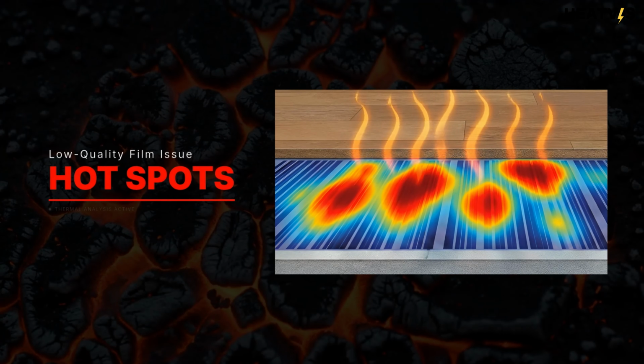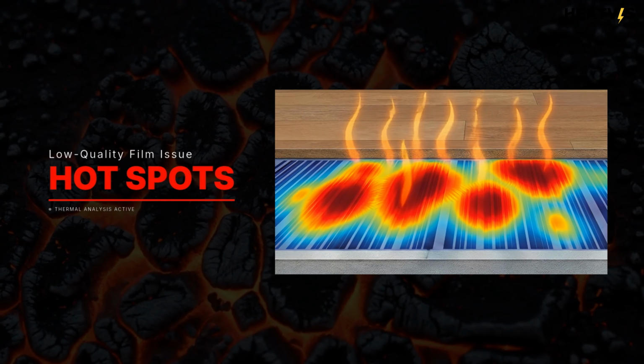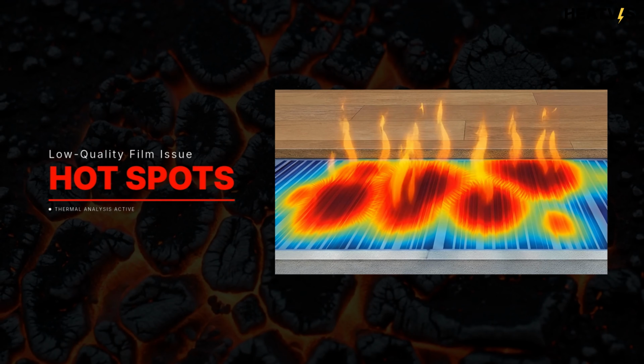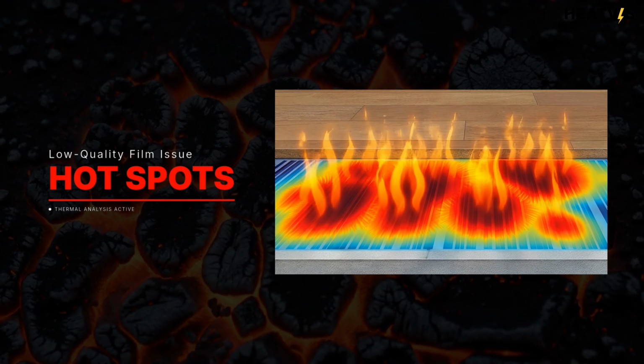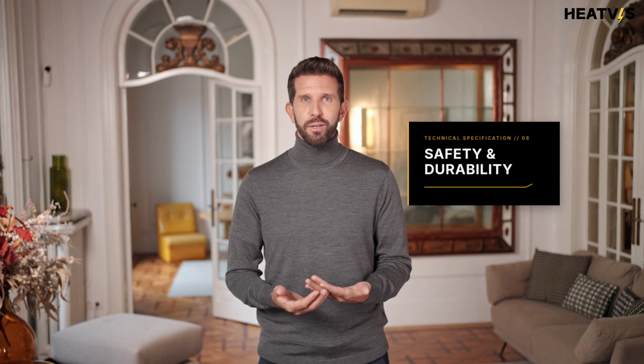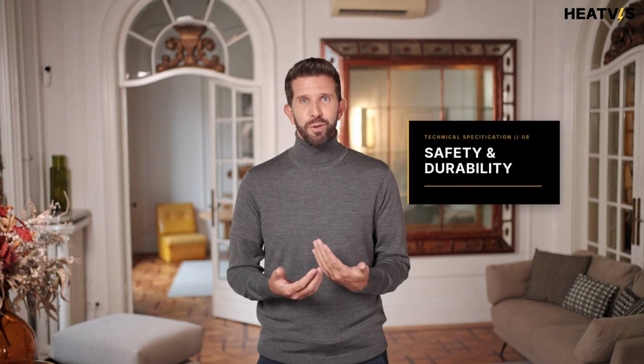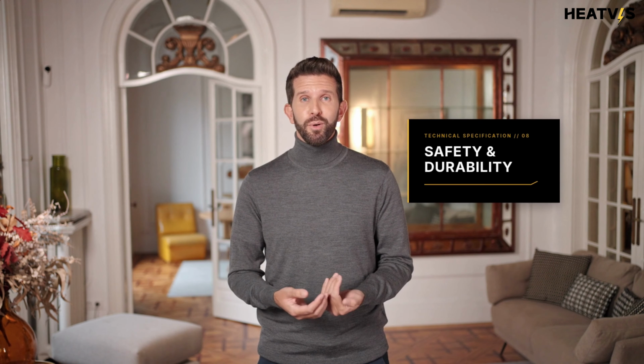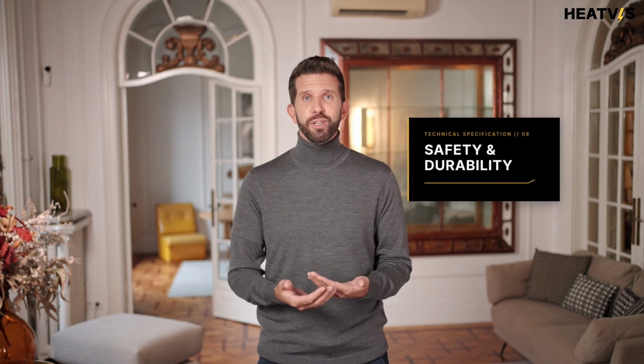In low-quality film, poor dispersion or impurities can cause current to concentrate in specific areas, leading to localized overheating, hot spots. Hot spots aren't just small warm points. Over time, they can lead to floor discoloration and reduce product life. So carbon quality affects not only efficiency, but also safety and durability.